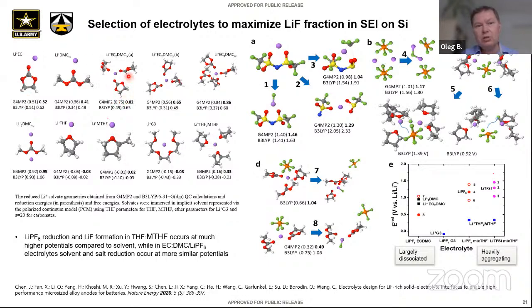EC in this case gets reduced. If we reduce DMC, you can see that it's bent. Then it's 0.65, which is consistent with DMC reduction being lower, right? Also, DMC contributes less to the first solvation shell, which is another relation to the importance of understanding the solvation shell. So EC is going to reduce first, and if we go to a larger system of 4, it's a similar reduction potential as with 3. So EC will have reduction potentials in the range of 0.8 from calculation. Experimentally, it's close to 0.6.